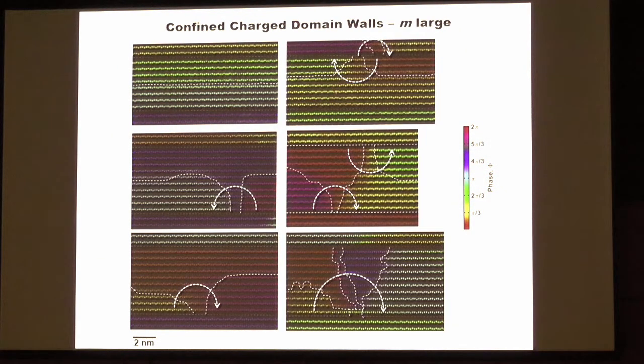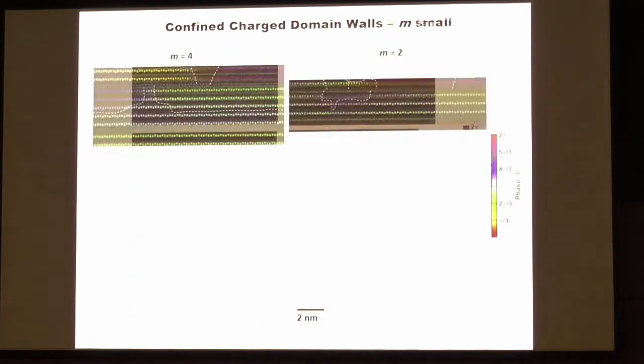We can also see what happens as these come close to each other. Here you can see these may come close across this double iron layer, where you can get multiple domains in close proximity. You can also see within this single lutetium ferrite block, the domains, the phase may wind going through in unusual configurations. And then very rarely we may get all of the domains wrapping around a single point.